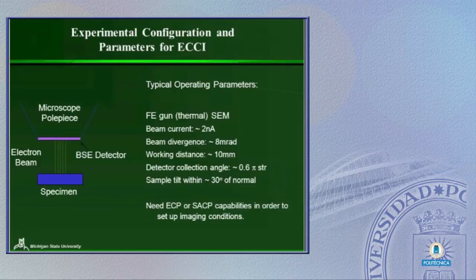The field emission gun, because it's a thermal gun, gives us a pretty good beam current, and that's been a big advantage to us. We have a beam divergence of about 8 milliradians. We work at typical SEM working distances, and that makes our life really nice, because what we're able to do is use various deformation stages, things like that, that would be much more difficult to do if we were in a high tilt configuration, and quite frankly, impossible to do if we were doing this in a TEM.